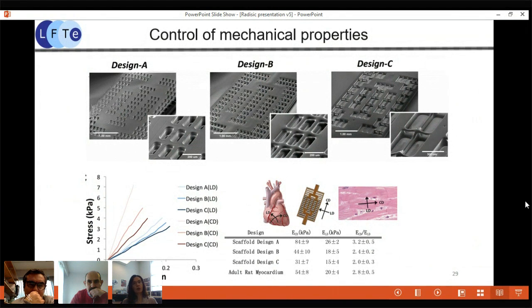So for example, anisotropy of mechanical properties is very important for cardiac tissue because in the long fiber direction, the tissue will be much stronger than in circumferential fiber direction. And so through this angiochip design in scaffold B, if you look at these numbers in B and compare that to adult rat myocardium, we are able to mimic the mechanical properties of the actual myocardium. And you can do the same thing for liver or any other tissue that you are interested in mimicking.